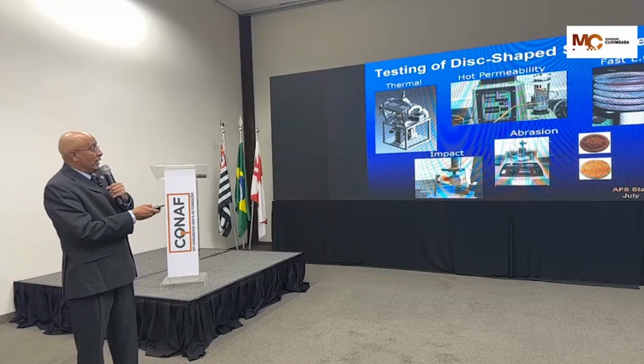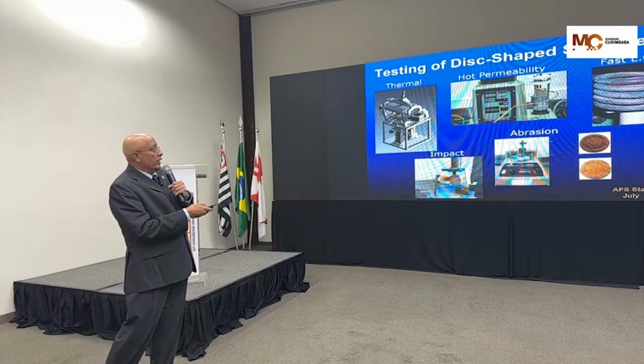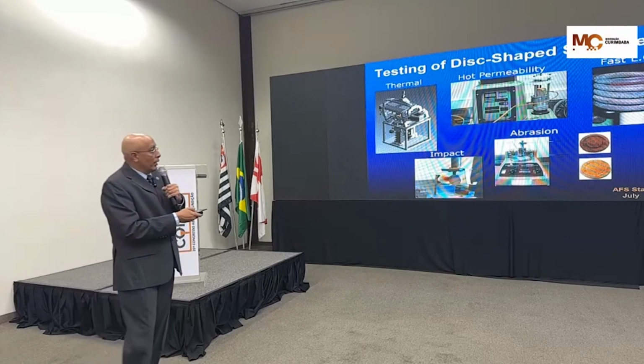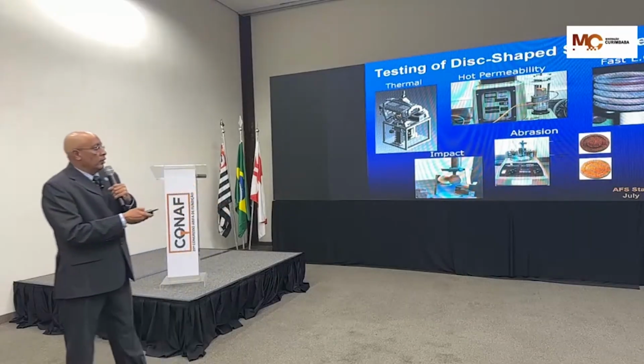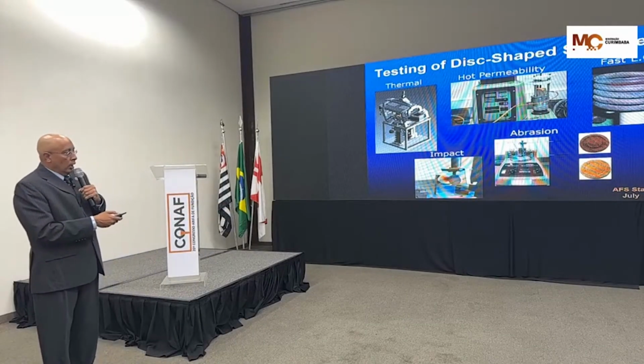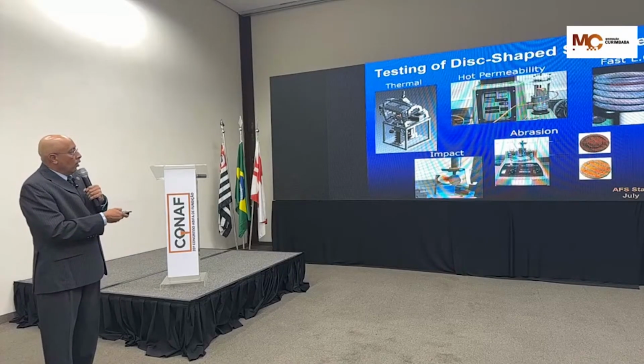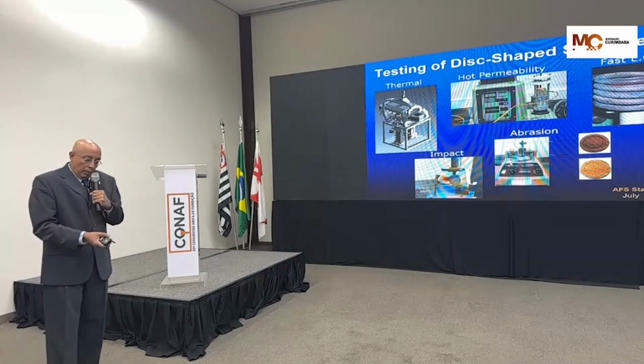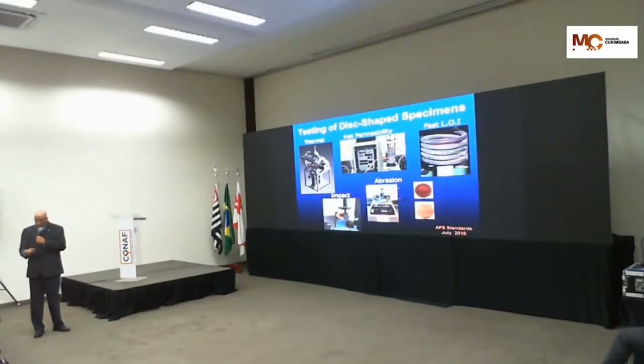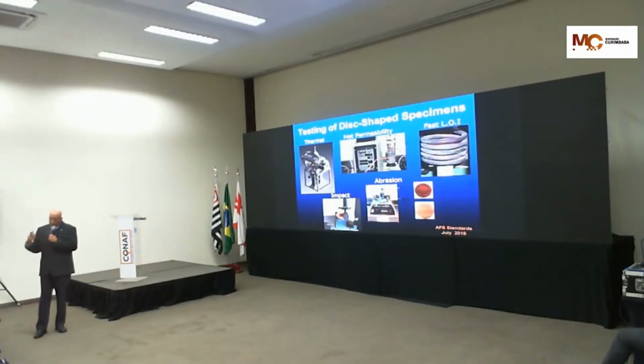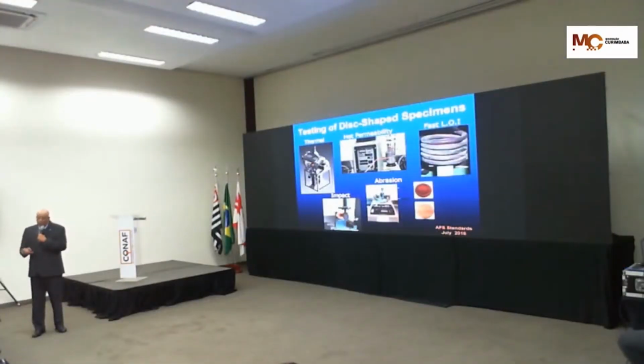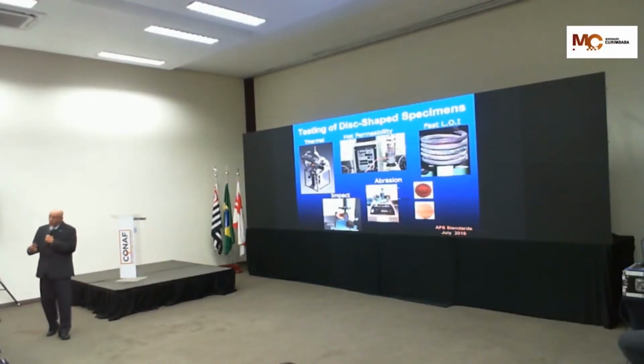We have 5-minute techniques, meaning in 5 minutes we can get the total organics, the volatile chemicals, as well as the moisture measured in your specimens, and to characterize the impact strength of the cookie at room temperature. This particular test can tell us the strength of our mold and cores. Why we look at impact for toughness is because in shakeout, we need impact energy, and the impact energy after the retained strength will give us the amount of joules required for shakeout if needed for that mold or core.